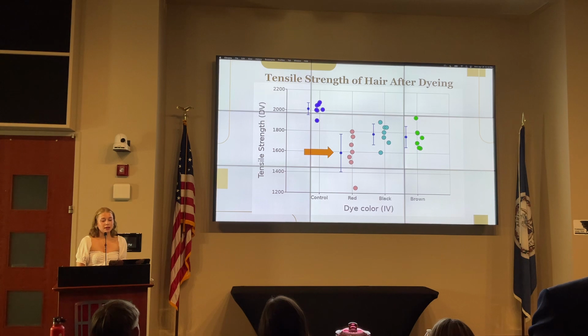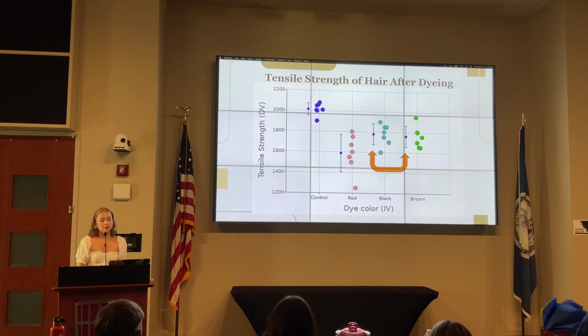The red dye group had the highest variance between each hair sample's tensile strength. This caused the red dye group to have the highest standard deviation and highest standard error of the mean. Despite the widespread data, it had the lowest mean, meaning that it was the most damaged group with the lowest average tensile strength. The black and brown color groups experienced almost the same amount of damage, leaving them with very similar means because of their very similar tensile strength. Consequently, there was no significant relationship between those two dyes because they caused roughly the same amount of damage.